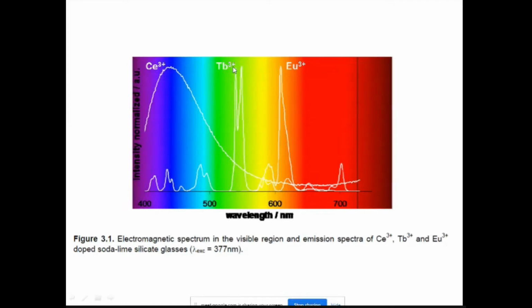One gives blue color, one gives green color, the other one gives red color. And now, if you combine these three elements properly in a proper composition, you will get a beautiful light. And similarly, if you are adding only cerium, you will change the blue color: light blue, thick blue, average blue, like that. So you can choose these ions and an environment, so that I can optimize the glass composition and rare earth ion concentration. I can get either white light, or blue light, or green light, or red light. So the color density and so on, I can do all those things.